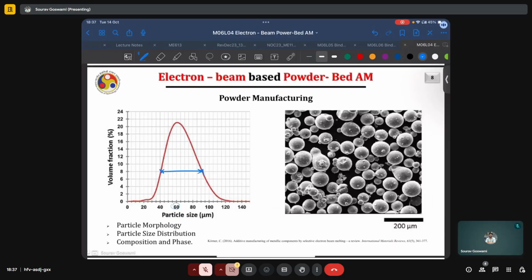On the right here, we also have what I think is a scanning electron microscope image of powder particles, which I presume is the feedstock for the printing process. Here we see how there are a few particles which are very nicely spherical, whereas others have a more elongated shape. And again, what is obvious is the wide distribution in sizes of these powder particles.